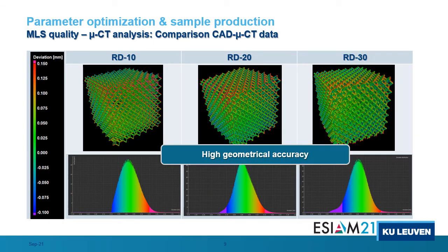Micro-CT analysis was also performed to evaluate the differences between the produced coupons and the CAD geometries. The results presented in the pictures of this slide show good agreement between the produced part and the CAD, indicating high geometrical accuracy of the manufacturing process. The small differences captured by the micro-CT analysis can be attributed to the dross formation and to the unmolten particles attached to the external surface. Apart from the slight increase in internal porosity of RD30 coupons and these small geometrical deviations, we can conclude that we achieved our goal of building accurate, high-quality lattice structures with this aluminum alloy.